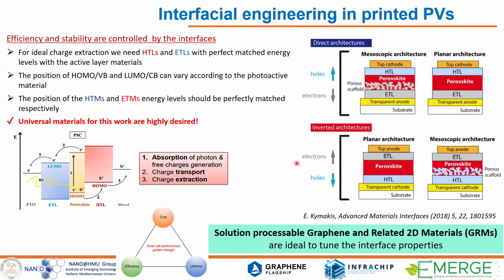Okay, just to close the overview. In the last 10 years, we participated in the Graphene Flagship. We are developing 2D materials, and we integrated 2D material interlayers and dopants across the typical solar cell structure, either doping the perovskite or forming an interlayer between the active layer and the transport layers. This integration helped us to improve the power conversion efficiency, but most importantly, the lifetime stability of the solar cells and modules.